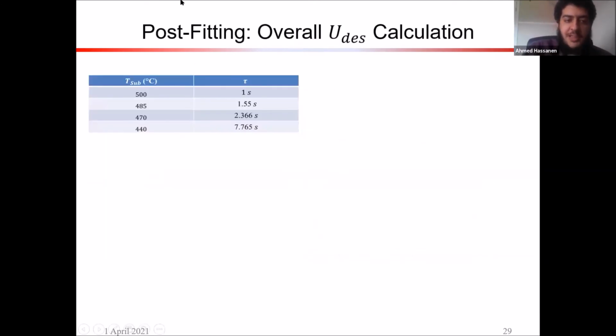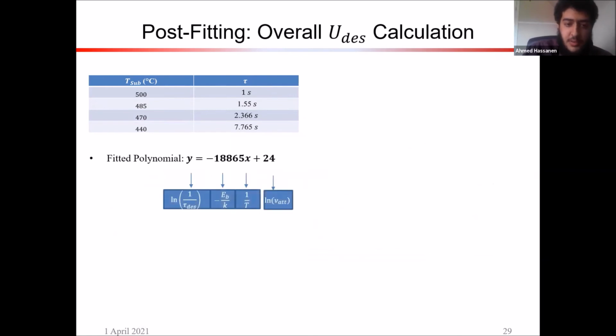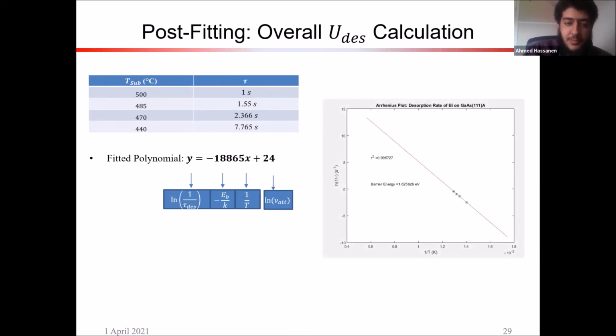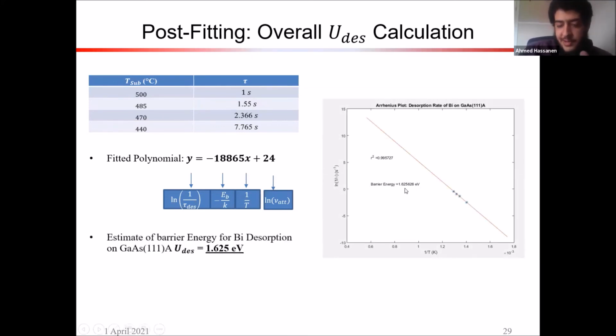And so, as you can imagine, doing this for several temperatures, we get different tau values. And as you can see here, it actually increases the more the temperature decreases. So that is logical. It takes longer the colder it is. And so just taking the ln of all these values and then plotting the linear Arrhenius plot, and taking this slope, we can find that the barrier energy is around 1.625 electron volts.